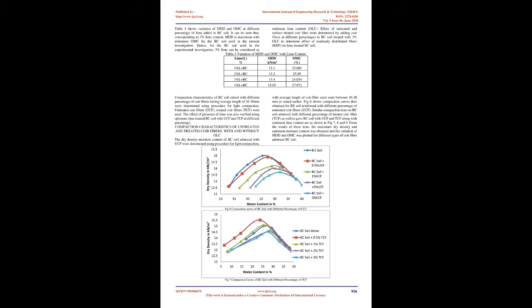Water absorption characteristics of surface-treated coir fibers. Water absorption of untreated, alkali-treated and alkali-treated with water-based epoxy resin-coated samples of coir fibers were determined by immersing all the three in water up to 90 days. Initially the dry weight of the fiber is taken, then the wet weight of coir fibers at the end of each curing period was noted, and finally these fibers were dried in oven for 6 hours at 60°C and the weight was noted down. The water absorption of coir fibers was determined in percentage as the ratio of weight of water to the weight of dry fibers 22, 23 and 24.